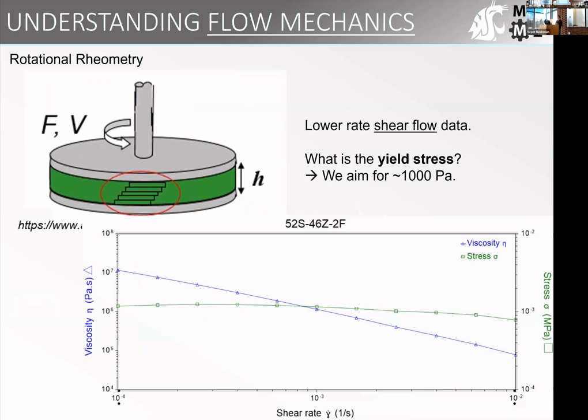Okay, so in shear rheology, we're doing lower rate shear flow data. So we have a material that's undergoing 100% shear flow. We assume that no slip is happening. And we use this to determine the yield stress. Of course, we're going to use the data in our model as well, but we want to make sure that we have a material that can reasonably be printed with. We aim for about 1000 pascals, which is what we're seeing here in our newest composition.